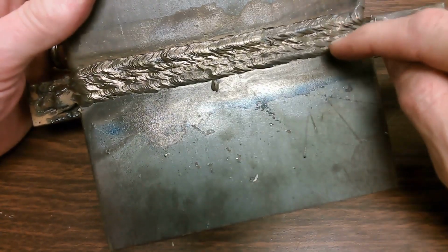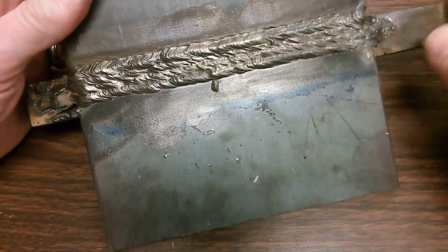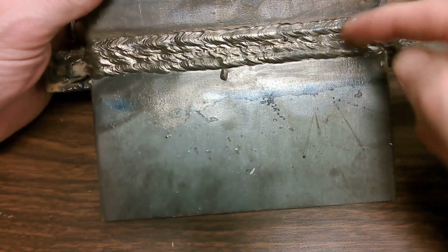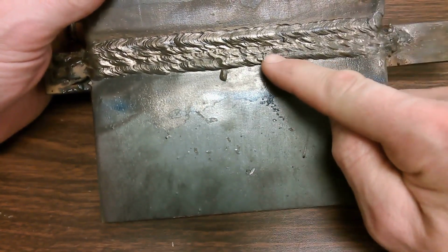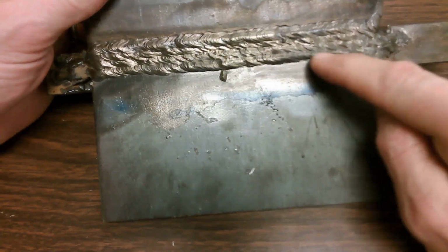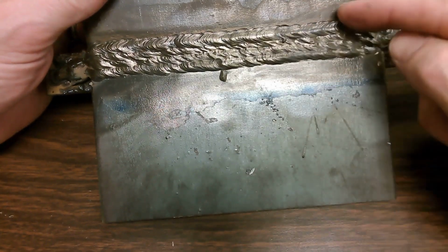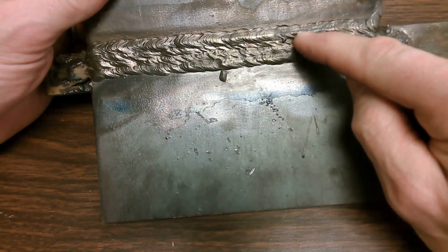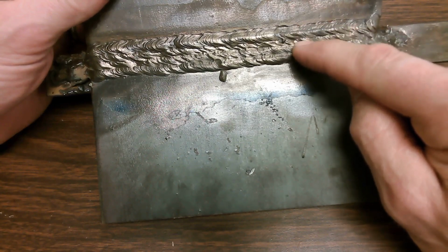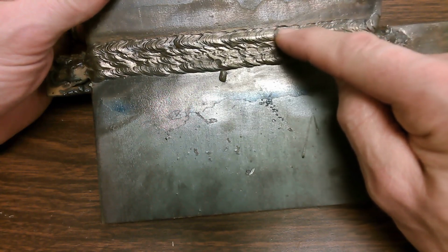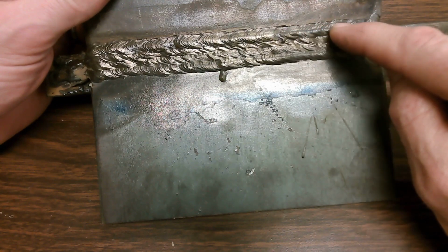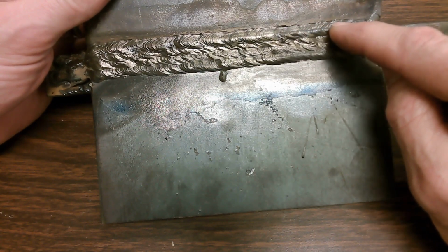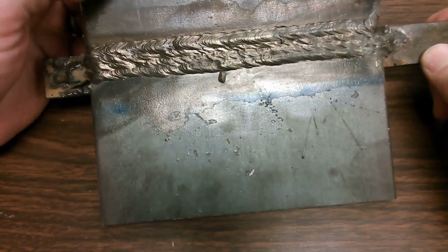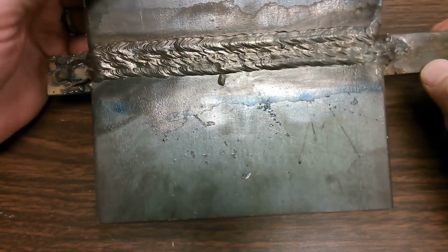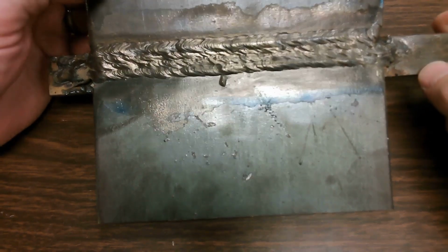There's 4 beads there. This is a horizontal weld, so this would have been the bottom, this would have been the top. They would have done this bead first, second, third, working that progression up. You can see this is the last bead because you can clearly see the entire bead there. Notice a little bit of undercut at the top. That's something we're going to look at and measure. That's very typical, very common on a horizontal weld.